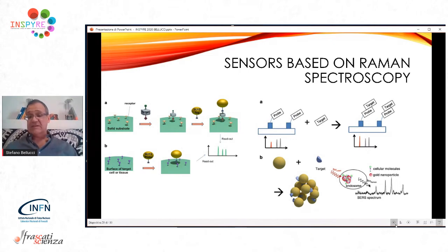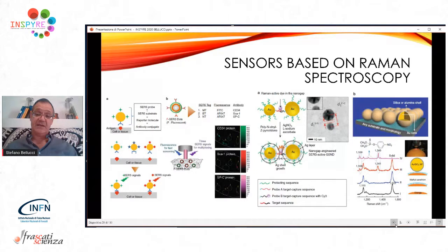It's too small. So by putting these molecules on an engineered nanoparticle substrate, you can obtain a distribution of what are called hot spots. On these hot spots, typically in the position of the nanoparticles on the substrate, the molecules that are being deposited give us a signal that can be 1,000,000 times higher than the normal signal that would be given on a standard surface without nanostructure. So that gives us the possibility of